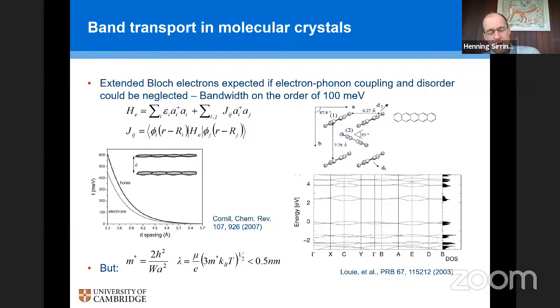And on the bottom right, you can see the calculated band structure of pentacene. And what you immediately notice is, of course, that this doesn't look like the band structure of silicon. And the main difference is that the bands are really flat. The band dispersion is not several electron volts, but only on the order of maybe half an electron volt as you go across the Brillouin zone. And the reason for that is, of course, that these molecules in the solid state are relatively far apart from each other. The typical intermolecular distances, the pi-pi stacking distances, are on the order of 3 to 4 angstrom.